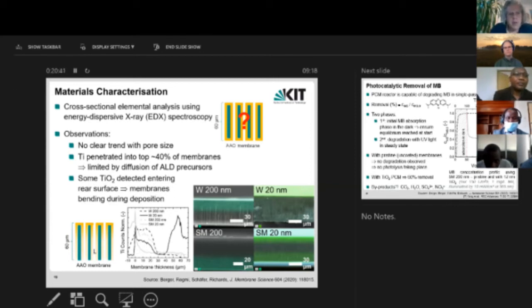So in the bottom left-hand corner is a rough schematic of what the membranes more likely look like with their titanium dioxide coating. There is a large amount on the top surface, reducing throughout the thickness of the membrane structure, with possibly some titanium dioxide being deposited onto the rear.